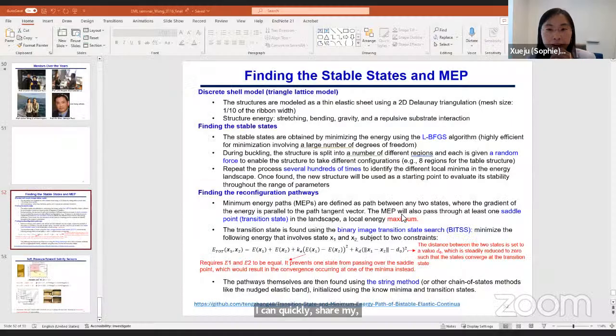That's a great question. So basically what we did, in collaboration with Teng here, we minimized the energy of the structure. We cannot say we do not miss any single stable states, but we tried our best to identify all the local minima as stable states. I can quickly share my screen for more information.